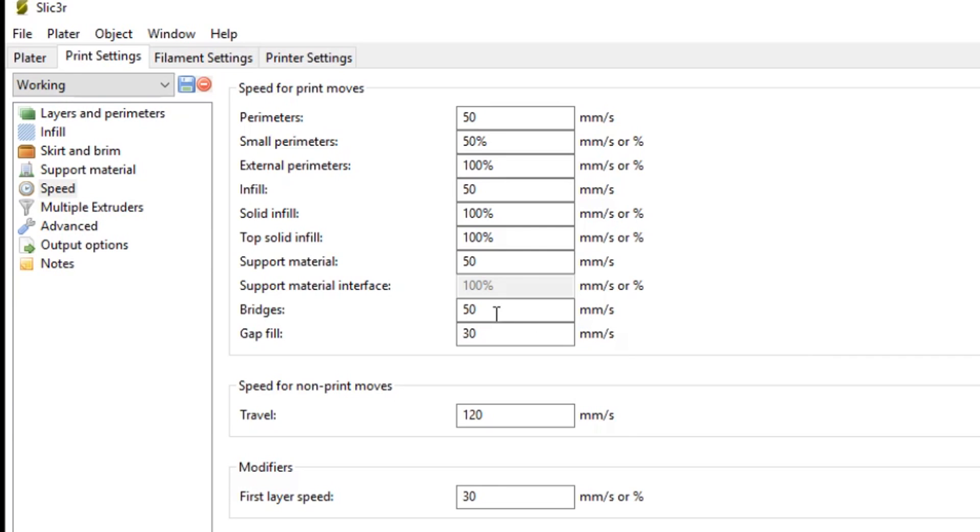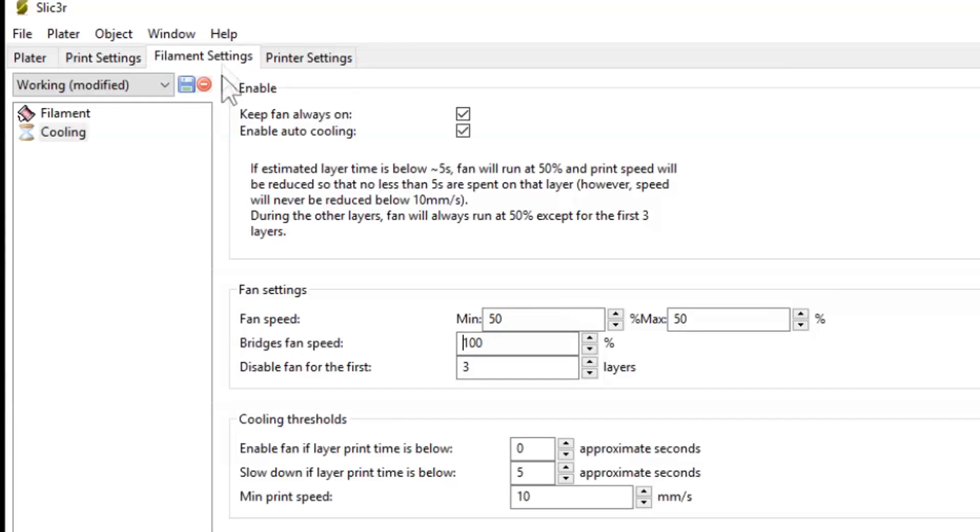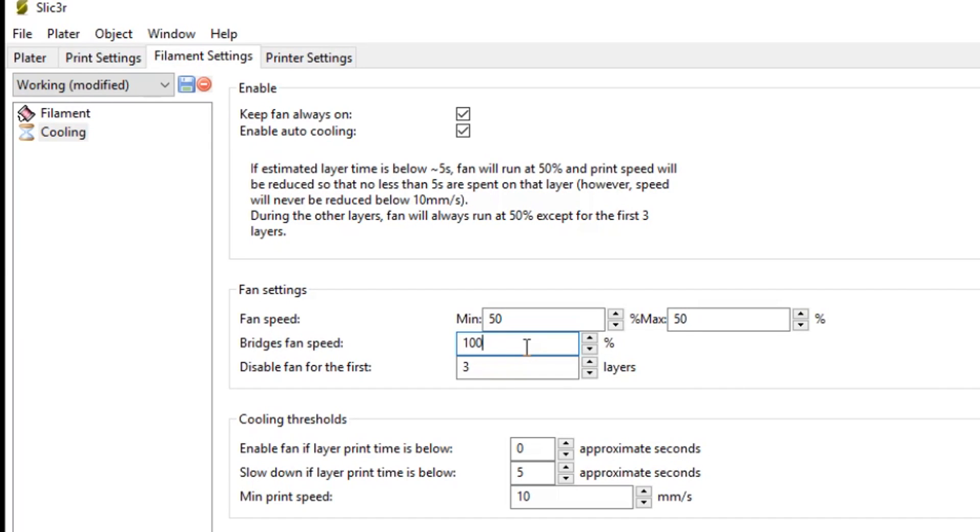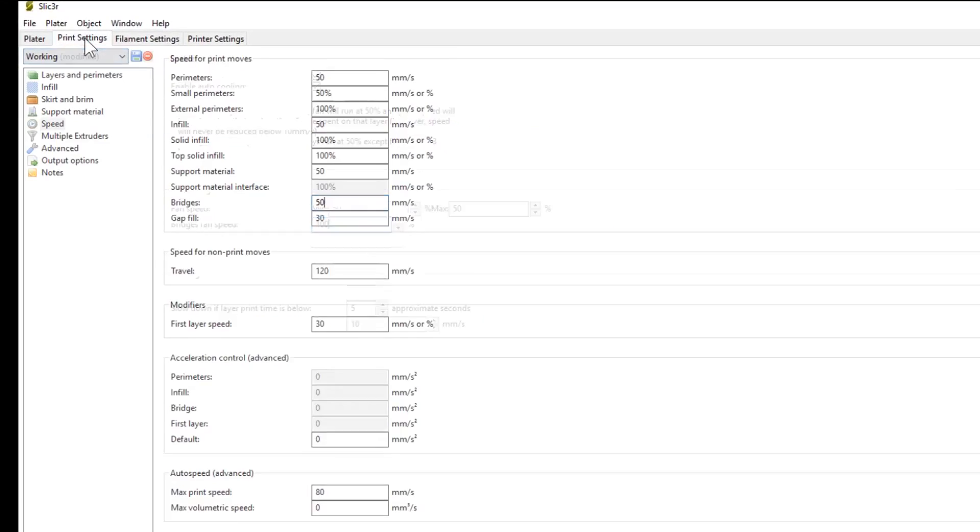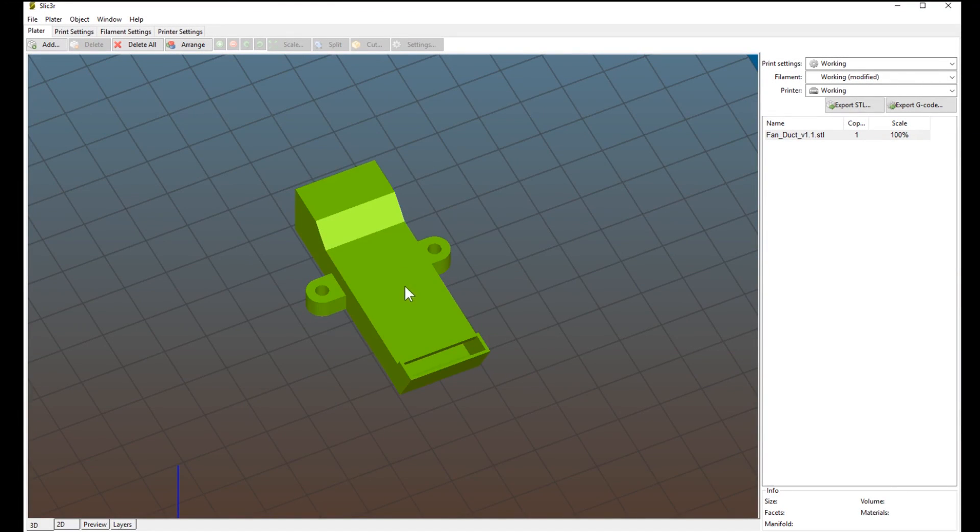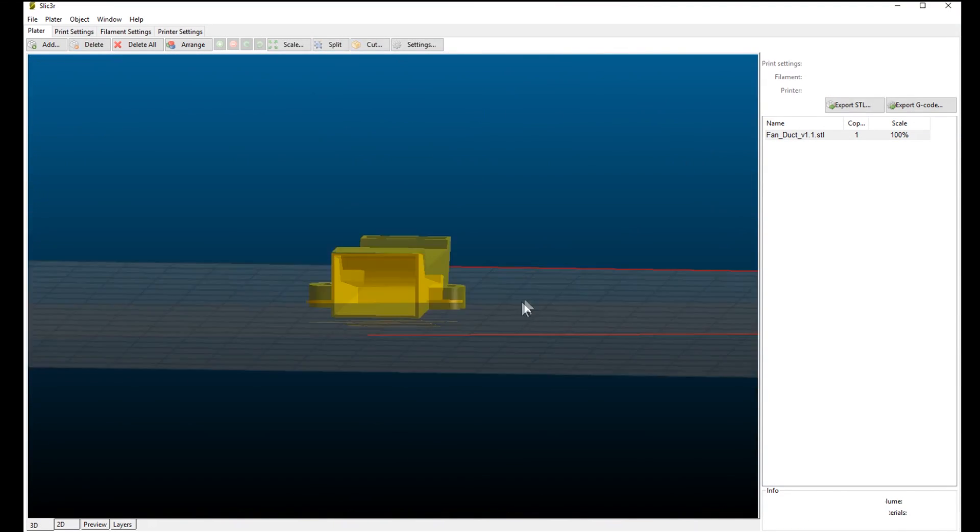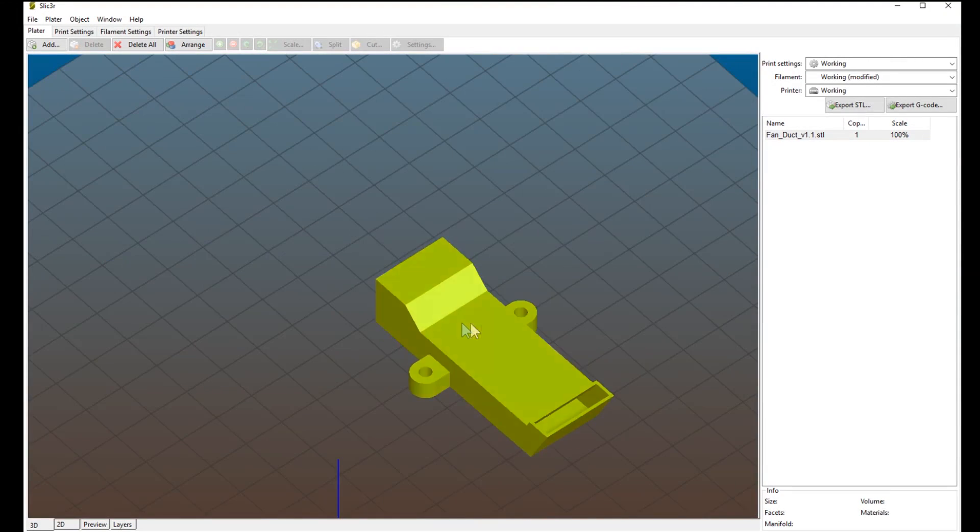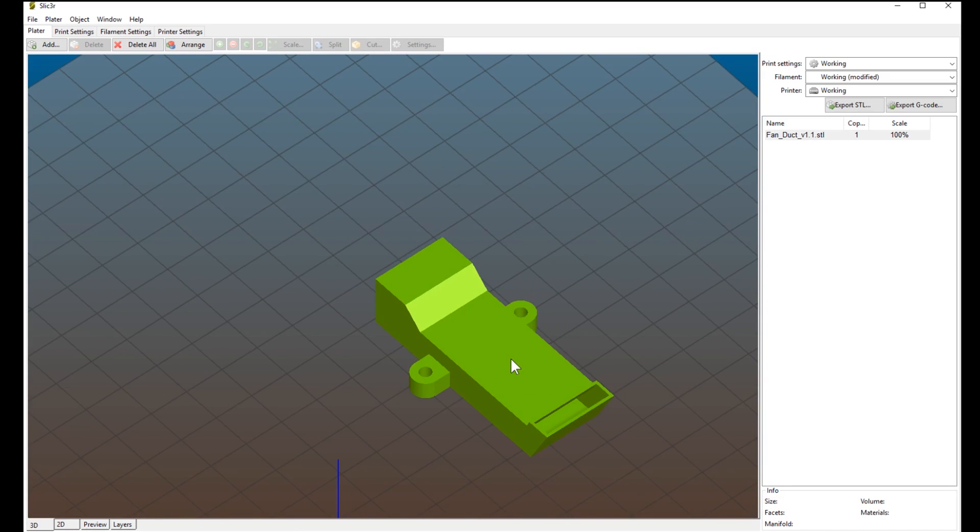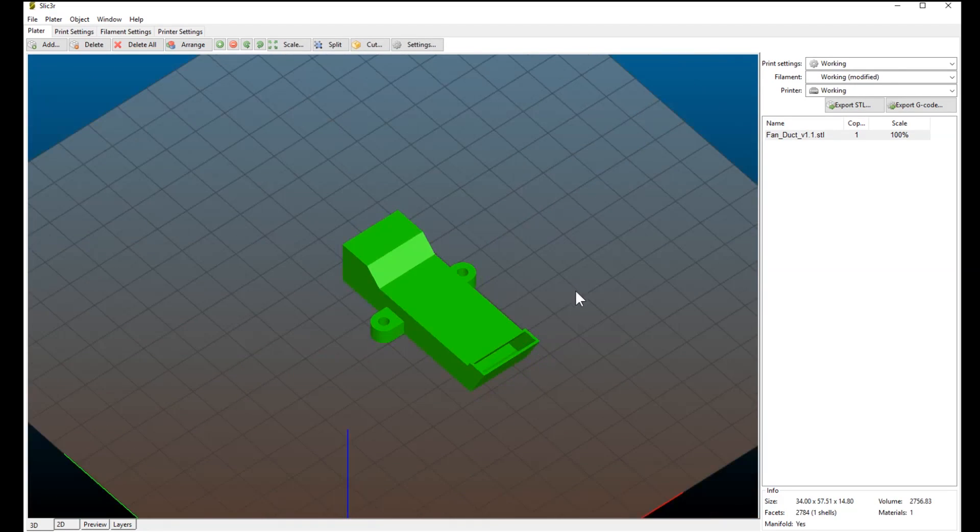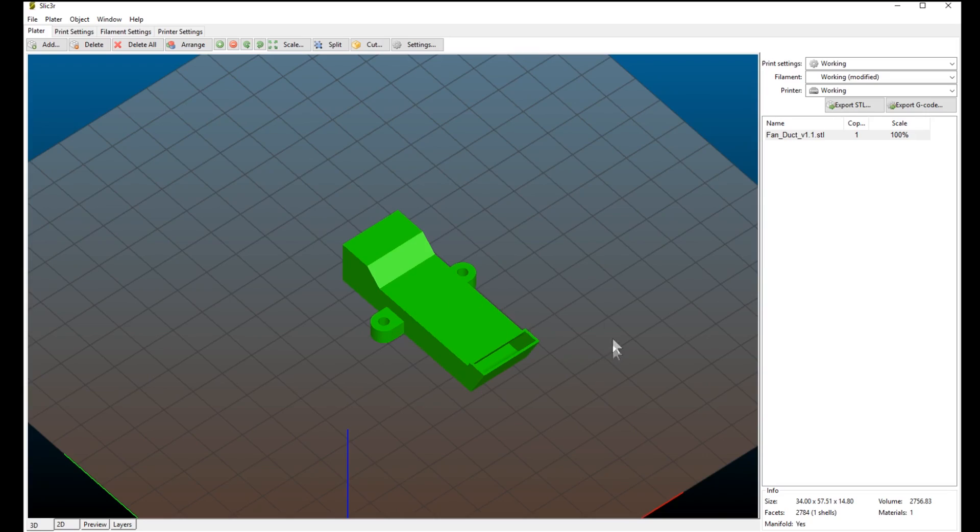You need that to be at least, in my case, 50mm a second to ensure that the print head is going to move nice and fast and the plastic isn't just going to droop if the print head is moving quite slow. The other thing that we need to ensure is the cooling. We want the bridges fan speed setting to go full blast, 100%. We want the plastic that comes out on that bridge move to go hard as soon as possible. So it doesn't just sag, it maintains its straight line. So we're cooling that plastic down and we're blasting it with 100% of air. Now I've tried to print this in Cura and unfortunately Cura doesn't see this particular part as a bridge. It just tries to print over this particular hollow section like a normal top or bottom surface. And that just doesn't work. So Slicer does a great job of identifying this as a bridge and uses those bridge moves to print this particular part correctly.